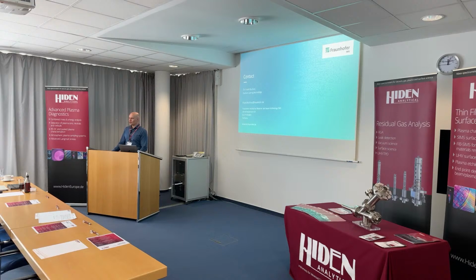Thank you. Welcome. Maybe, do you know the dopant ratio of your coatings? Yes, we know it, of course, what we have in the cathodes initially, which is 5 atomic percent. And then in the coatings for boron, we have exactly the same, independent of whether it's filtered or non-filtered. And for molybdenum, we have some change in ratio. Mostly we have some more molybdenum in the coating than it was originally in the cathode, but up to 10%, maybe 7 to 10, it's the highest. Of course, you have the heavy molybdenum. You expect some changes if you shoot the molybdenum deep inside the carbon. Then you have some sp2-rich traces or graphenic traces inside the material, which makes totally different properties.